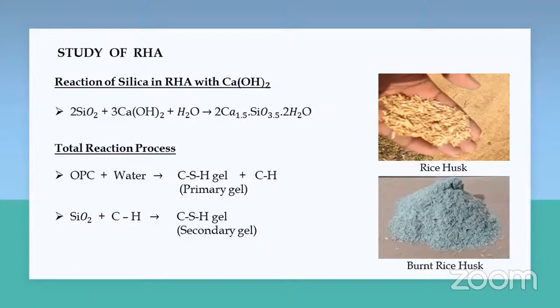Study of RHA. It is hoped that the use of RHA will reduce the amount of calcium acetate that is formed. The quantity of calcium hydroxide required to chemically react with PVA is decreased when amorphous silica in RHA combines with calcium hydroxide. This decreases the amount of calcium hydroxide required to generate calcium acetate, which lowers calcium acetate production.